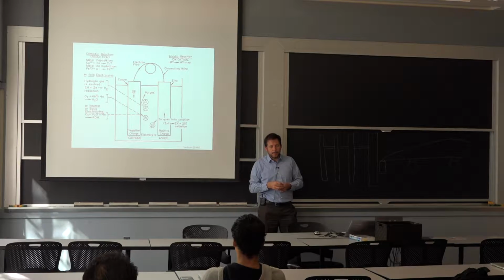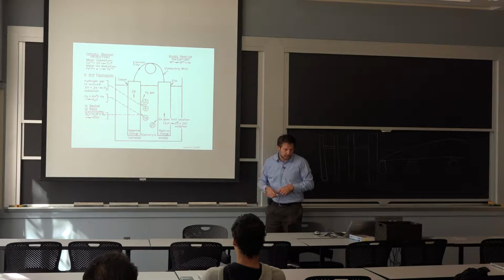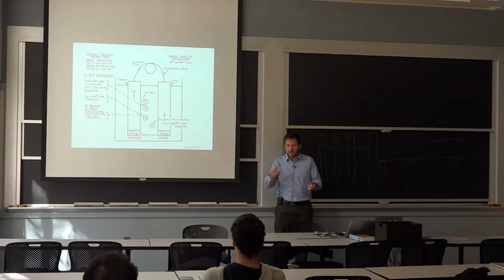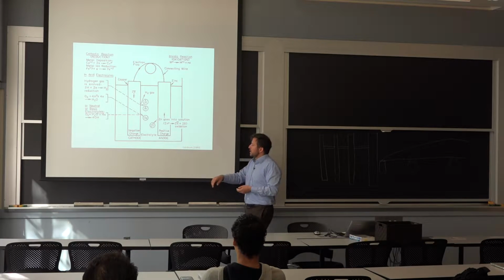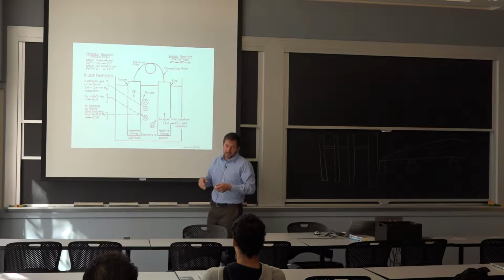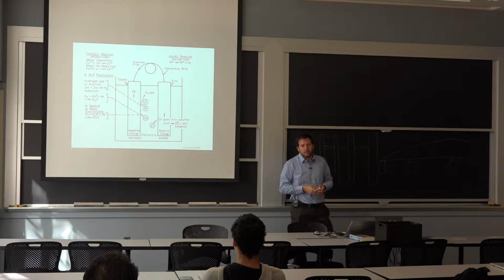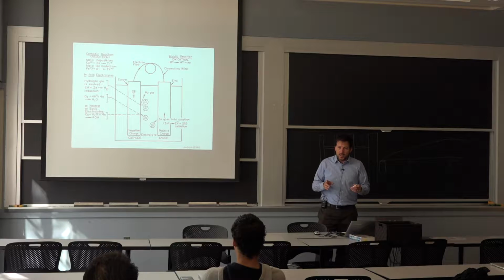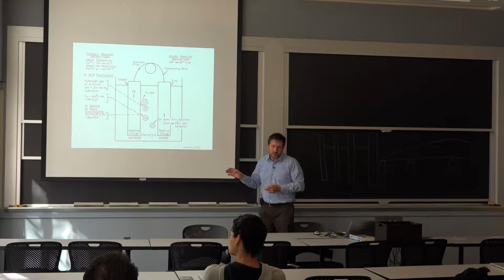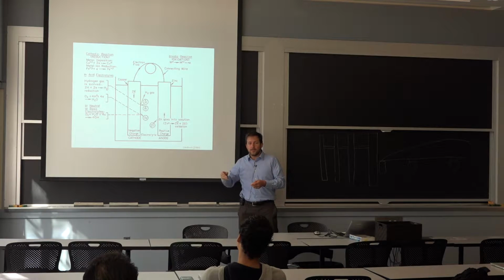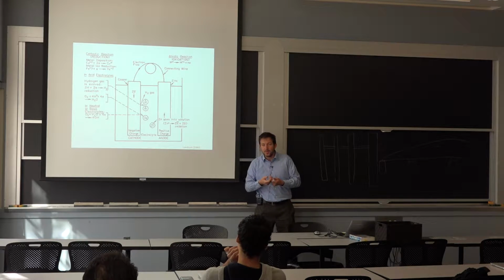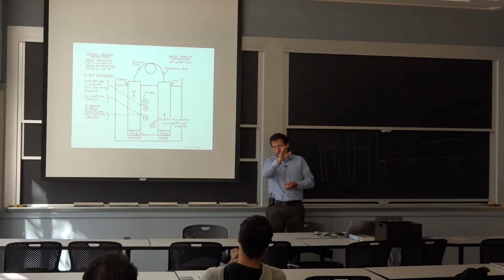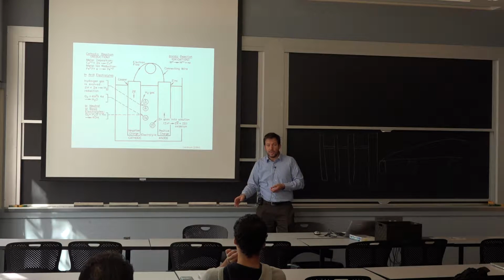If you have a defect in your coating, so when you put the beam on, it gets scratched, or you put the bolt, you expose some of the steel, that steel becomes a cathode automatically because of the difference in equilibrium potential. So it works as long as you always have zinc close enough to the place where you have the damage. So if you decide that you're going to remove the zinc layer over a relatively large area, well, the center of it may not get protected unless it's really in an immersed condition.